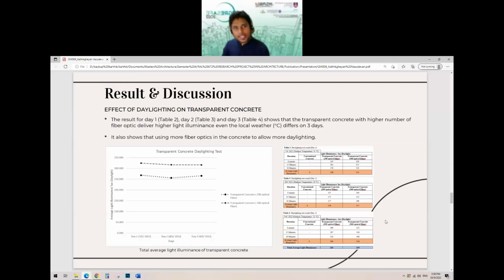So for the results and discussion, first is the effect of daylighting on transparent concrete. The table below shows the transparent concrete with a higher number of fiber optics delivers higher light illuminance, even though the local weather differs on the 3 days. It also shows that using more fiber optic in the concrete allows more daylighting. These are the results for the 3 days of experiment.